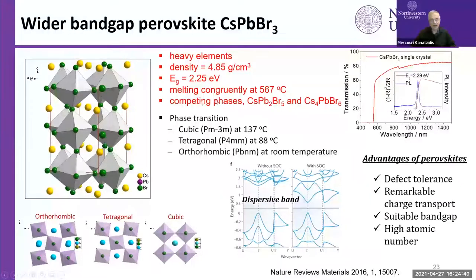Why? Because it has a band gap of 2.25 eV. That means you will have high resistivity in the dark at room temperature. Its density is not very high, but not very low, 4.8. So it's still acceptable. It melts at a reasonable temperature, 567 degrees C. And I point that out because CZT melts at twice the temperature. It melts at about 1200 degrees C. And that complicates the crystal growth substantially.